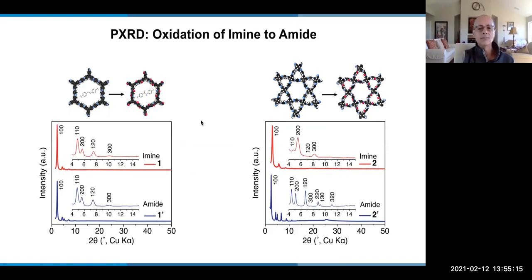But look at the crystallinity. This is the imine, and this is after it's been converted to the amide. Perfectly crystalline. In fact, more crystalline as you go to the amide. So this is approaching what molecular chemists can do. They can take their molecules, convert them into other molecules, and preserve their overall character. Here we can take our framework, and without breaking up the framework, we can go in and convert all the linkages in that framework to another linkage without destroying the crystallinity and the order of the structure.